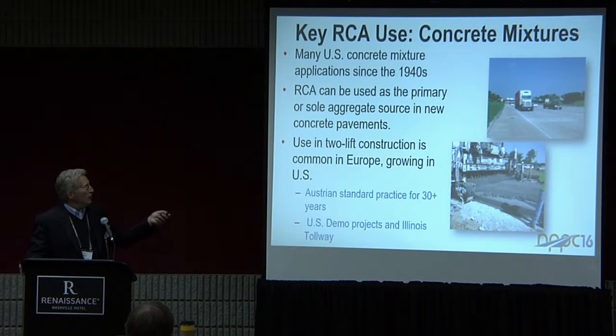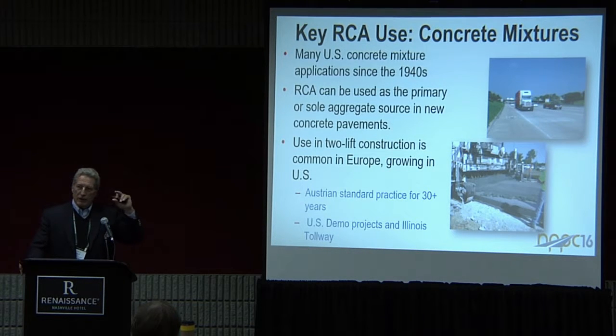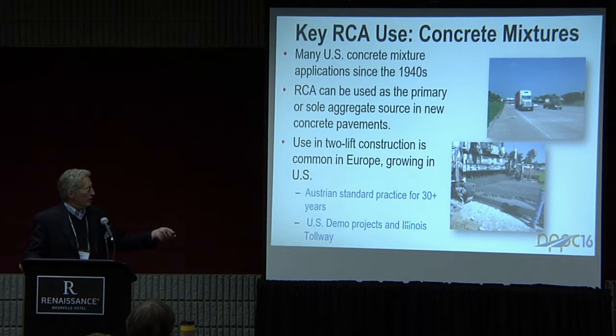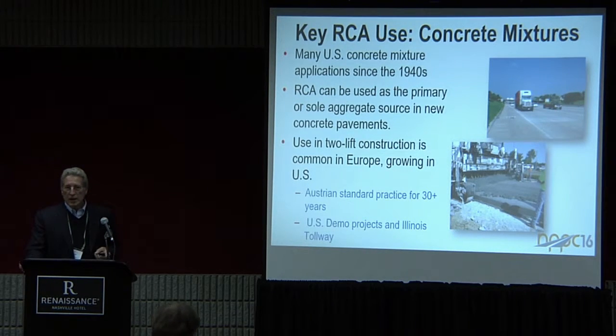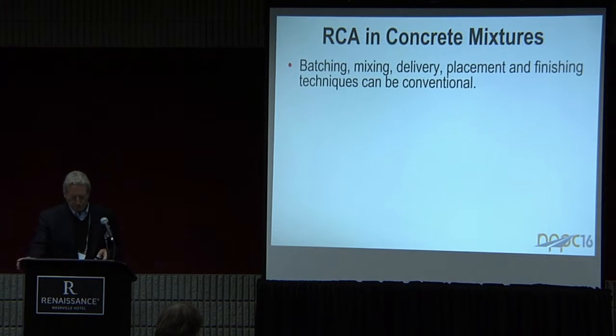We're seeing a lot of use in two-lift pavements, as I said. It's been a standard practice in Europe, particularly in Austria, for more than 30 years. They put it in the lower lift and put a high-quality, high-friction aggregate in the top 2 to 3 inches or so. And we're seeing some work being done here in Illinois, and the Illinois Tollway actually has adopted the use of two-lift paving on a wide-scale basis, as we'll show here in a second as well.